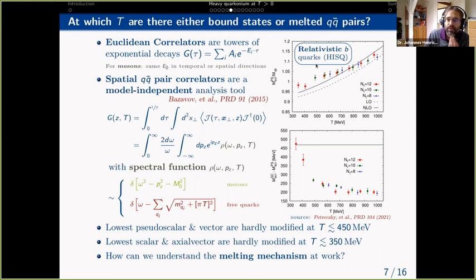What we did here is we used a relativistic formulation for the heavy quarks, explicitly bottom quarks, on the lattice. It's called highly improved staggered quarks, for the interested experts, and then computed the ratio of the eta b mass at finite temperature over the eta b mass at zero temperature. What you see is that up to a temperature of about 400 to 500 MeV, this ratio is essentially 1, which means that the eta b does not really feel much temperature effects up to 400 something MeV. Then you start to see that this is increasing, and we have here the curves for leading order and next to leading order temperature dependence, and you see that it begins to behave roughly as you would naively expect.